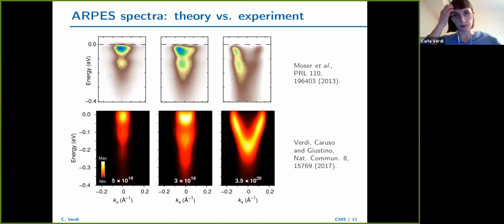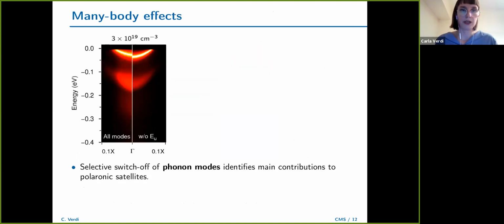Let me dive a little bit more in detail. So this is a comparison of the ARPES experiments that I showed you before and our own calculations. So you can see that we essentially capture what is observed. So at low and intermediate doping, we have these satellites, and at larger doping, we mainly have a kink and broadening of the band structure. We can do a bit more. We can actually examine the many-body effects in these calculations. So what is really going on?